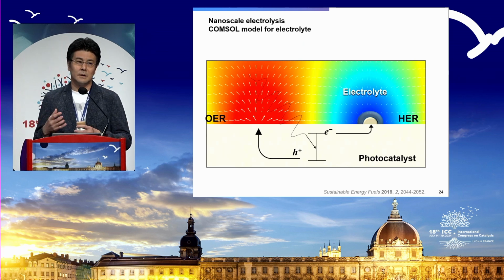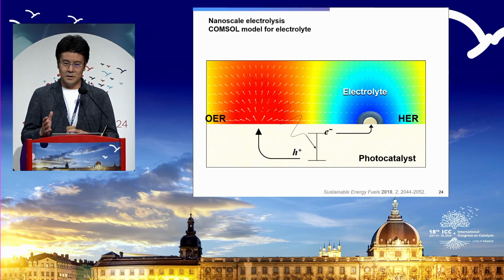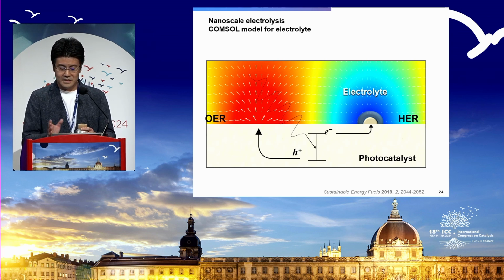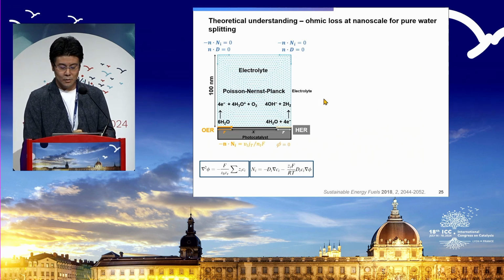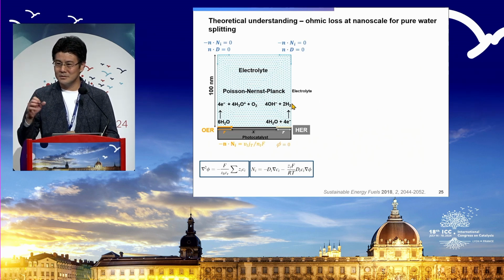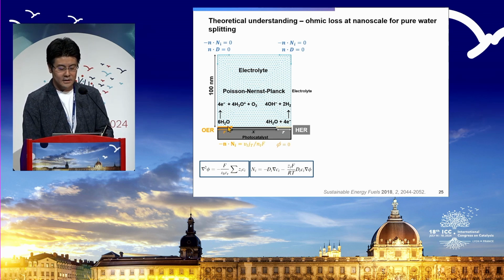So the next thing, as I said, is that the electrolyte property can determine the solution resistance and the pH gradient. We do nanoscale electrolysis, so we try to solve it by using COMSOL in this case. We put this nanoscale model, assuming the same surface is doing the reaction, so OER is here, and hydrogen evolution is here. Right? And let's see what happens in the electrolyte conditions. So this is the model that we use, and COMSOL needs to separate the meshes, so we try to use a supercomputer to make the mesh as small as possible. Here, again, the OER, and this is, again, the hydrogen evolution.